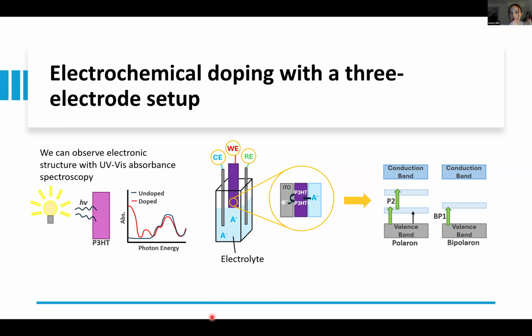And then it's all in an organic solution of a lithium salt. So when we apply potential with a potentiostat to the cell, we can remove an electron from the P3HT film, put it into the ITO substrate, and then anion intercalation will happen into the P3HT film. So the polymer is semicrystalline and it has crystalline and amorphous regions, and we expect the crystal structure to change upon doping, which I'll talk a little bit about later.